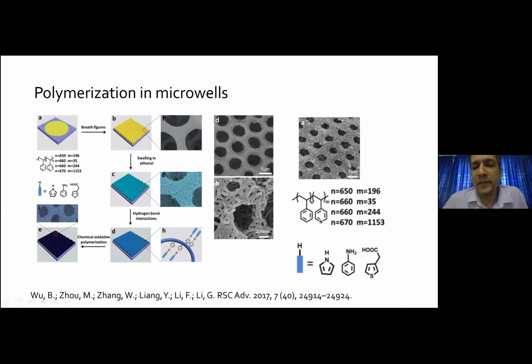Now, we made unsymmetric particles, and showed that unsymmetric particles can be made in these microwells of titanium chloride in the presence of water, forming titanium dioxide hemispherical particles. Similarly, people are curious whether polymerization can be done inside the system. So they first made the breath figure. Here they have taken polystyrene-block-poly(4-vinyl pyridine), and in this 4-vinyl pyridine, the nitrogen is a hydrogen bonding acceptor.